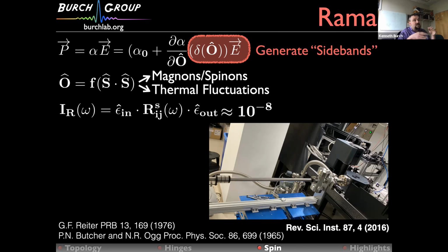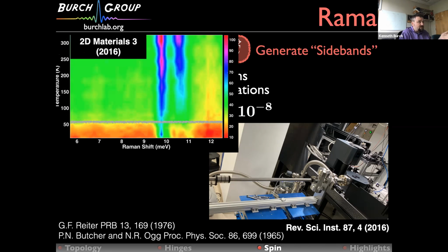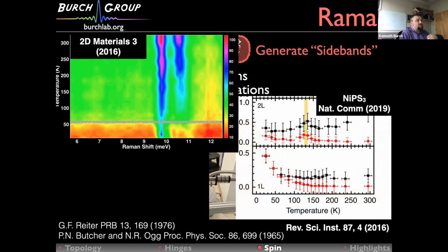What you'll see in that case is like a Debye-Waller factor when you do X-rays. Here, what you'll see is a broadening of the Rayleigh line, and that broadening is essentially from these thermal fluctuations. And indeed, we were able to use that. This is the Raman response versus temperature and Raman shift, and that green you see is not garbage. It's actually the thermal fluctuations from this 2D ferromagnet. We showed that you could use this to identify the order in 2D materials, because the thermal fluctuations gap out when you order. And very recently, that approach was used by Hyung-Sik Chung's group to show that in nickel PS3, it looks like the magnetic order dies when you go to the single layer limit, and it's probably in this BKT limit, which is quite interesting.